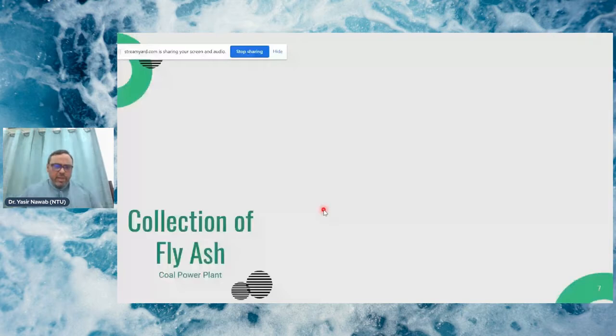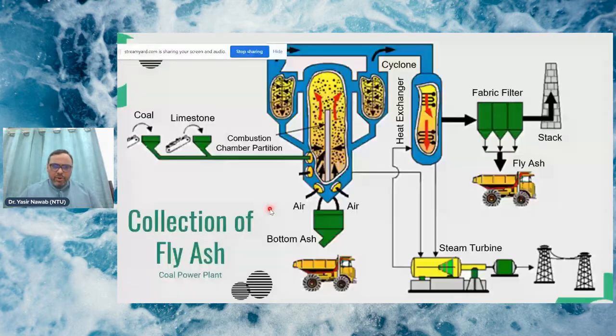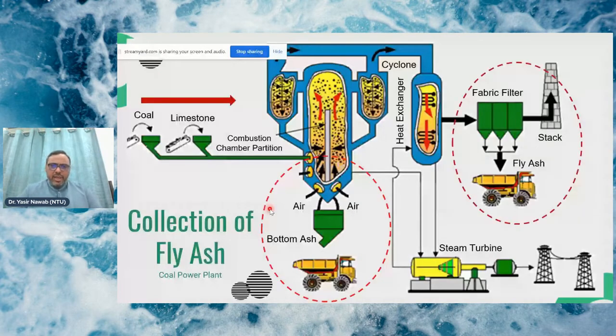So mainly, if we are talking about coal power plants, the collection of the ash is at 2 points. The first point is the bottom ash at the point of burning, and then the fly ash. In fact, it's from the filters. We collect it regularly, you can say after 8 hours each.